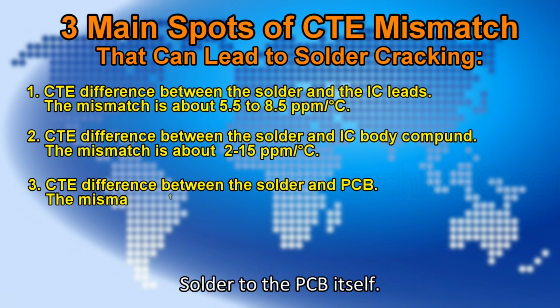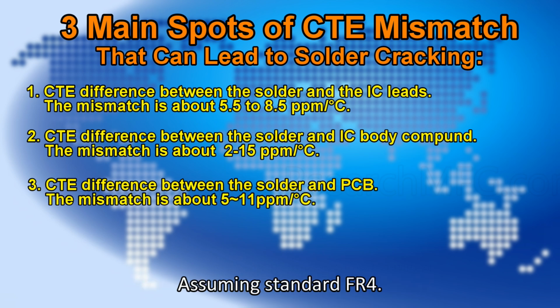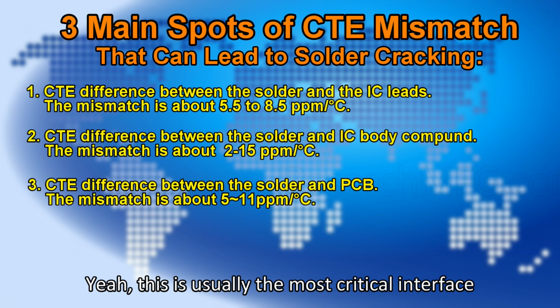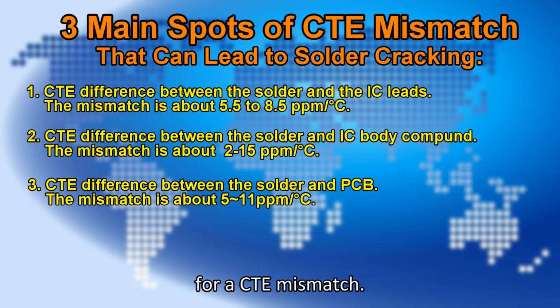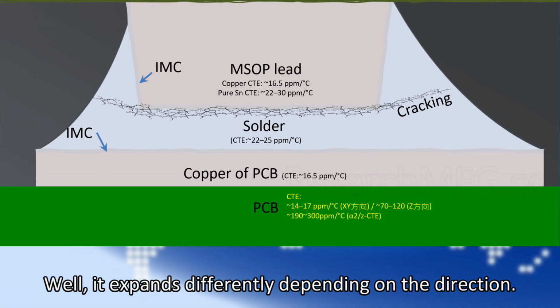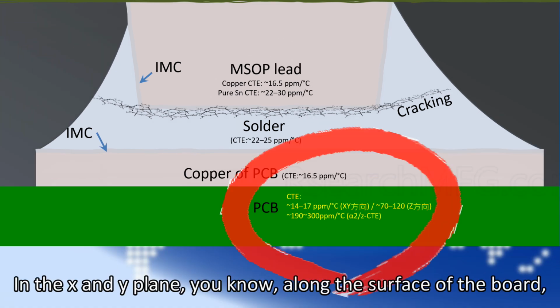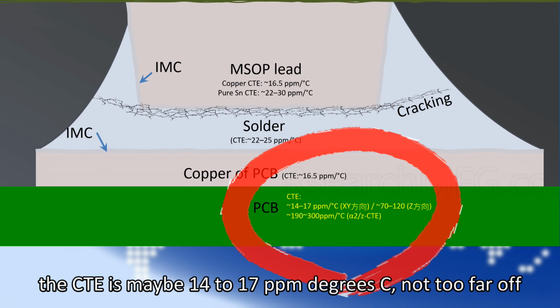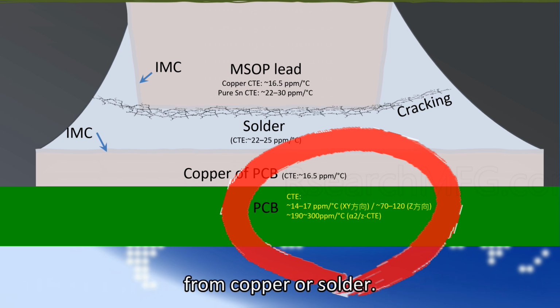That brings us to number 3. And this is often the big one, right? Solder to the PCB itself, assuming standard FR4. Yeah, this is usually the most critical interface for CTE mismatch. FR4, it's tricky. Well, it expands differently depending on the direction. In the X and Y plane, along the surface of the board, the CTE is maybe 14 to 17 ppm per degree C, not too far off from copper or solder.